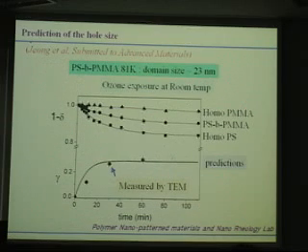If we are ozone exposed, then PMMA does not cross-link, so almost the thickness is the same. But in the homopolymer case, the thickness is decreased. For the block polymer, it is almost half between these. So we can predict the hole size.